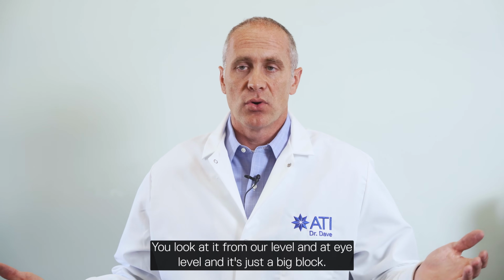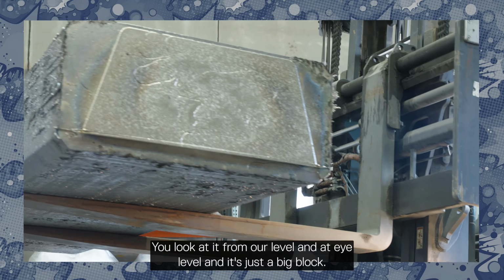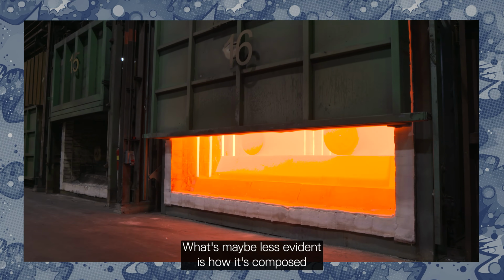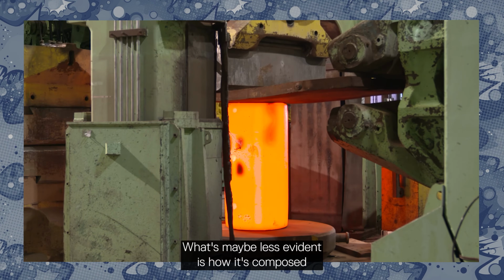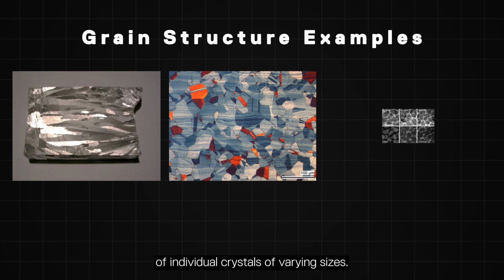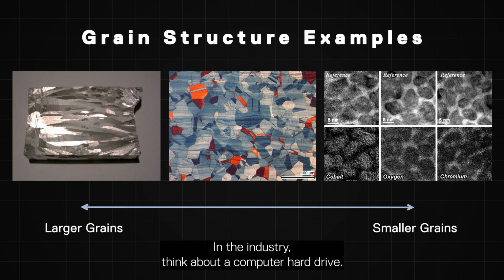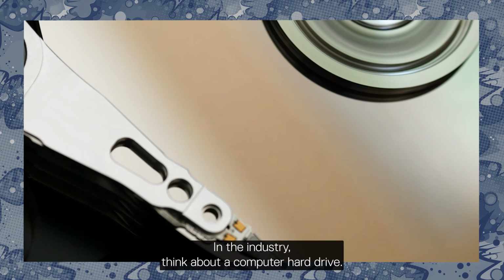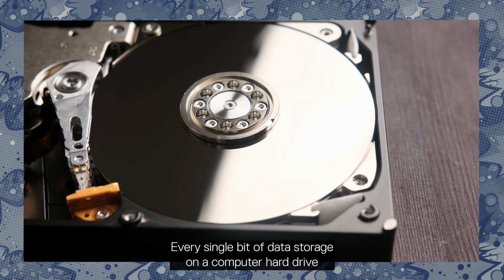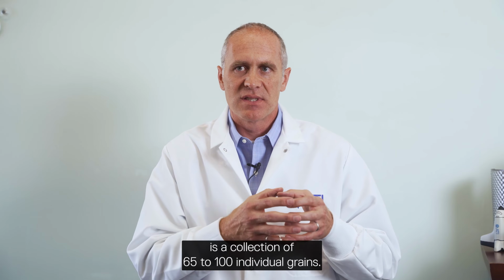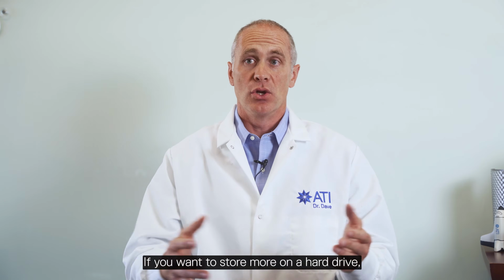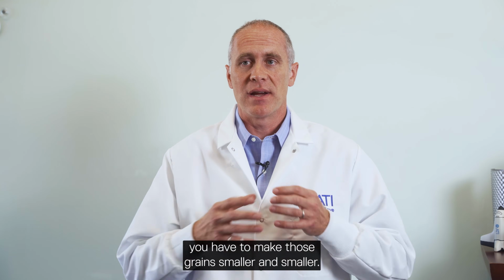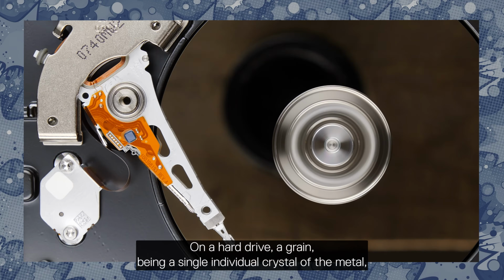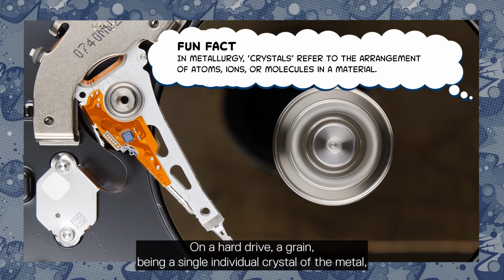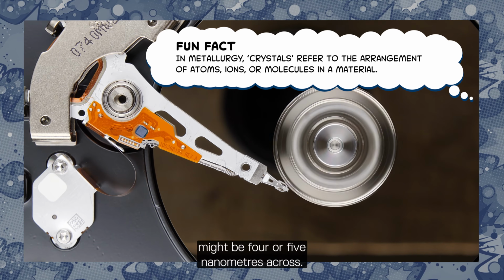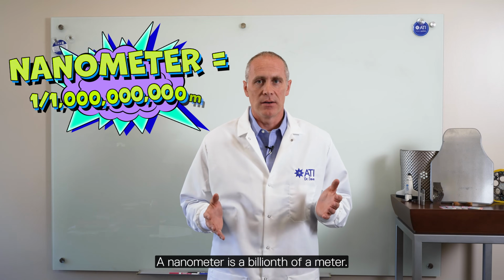Structure, what's a metal? You look at it from our level and at eye level, and it's just a big block, right? What's maybe less evident is how it's composed of individual crystals of varying sizes. So in the industry, think about a computer hard drive. Every single bit of data storage on a computer hard drive is a collection of 65 to 100 individual grains. You want to store more on a hard drive, you have to make those grains smaller and smaller. So on a hard drive, a grain, being a single individual crystal of the metal, might be 4 or 5 nanometers across. A nanometer is a billionth of a meter, right?